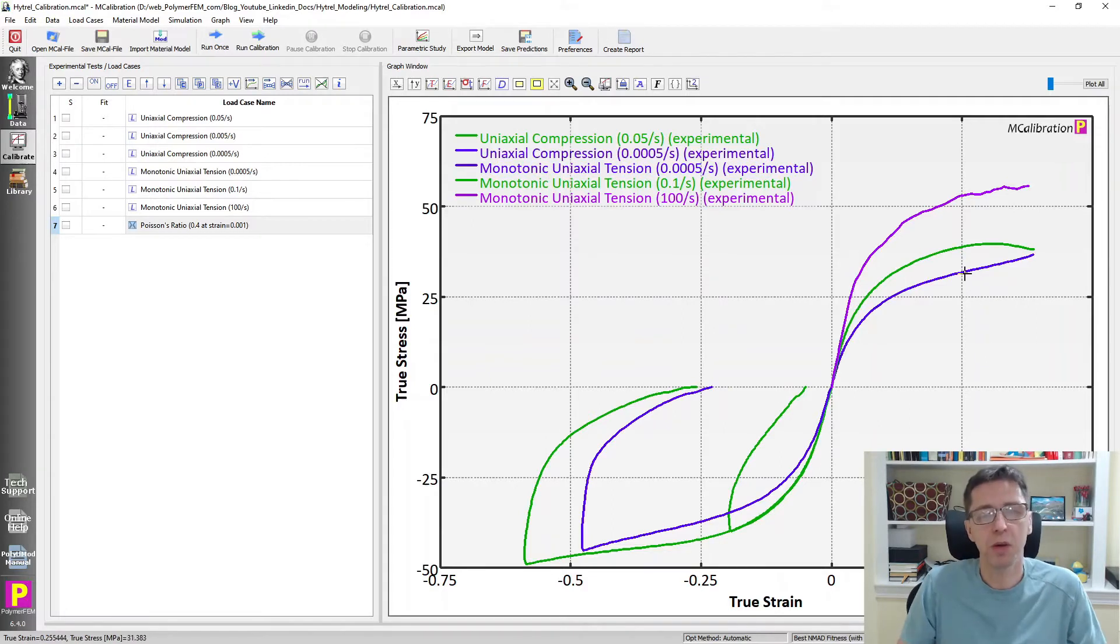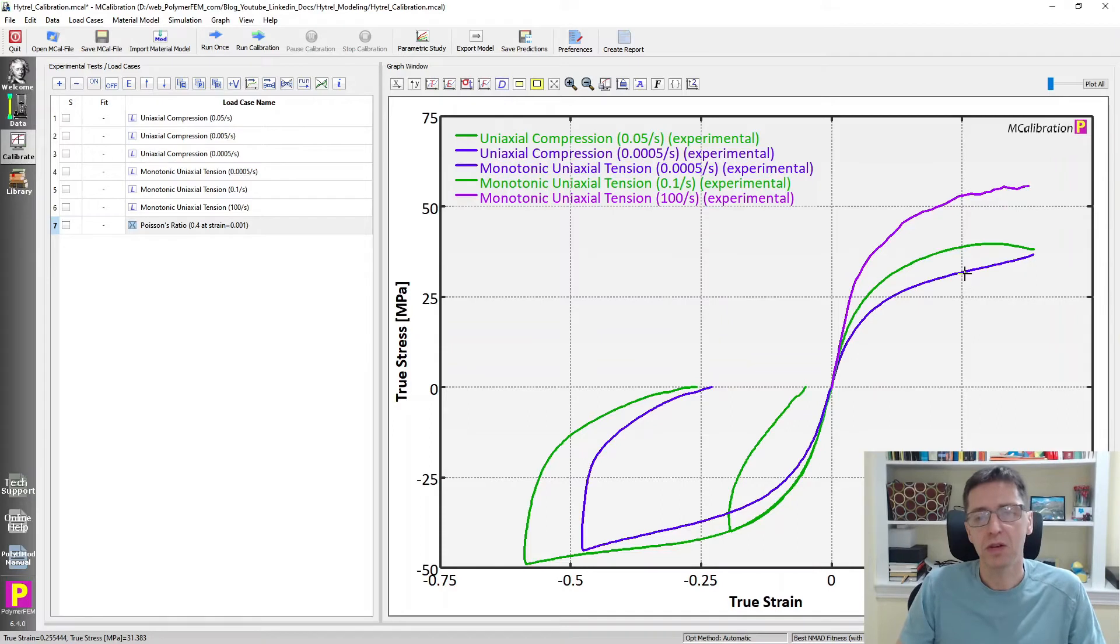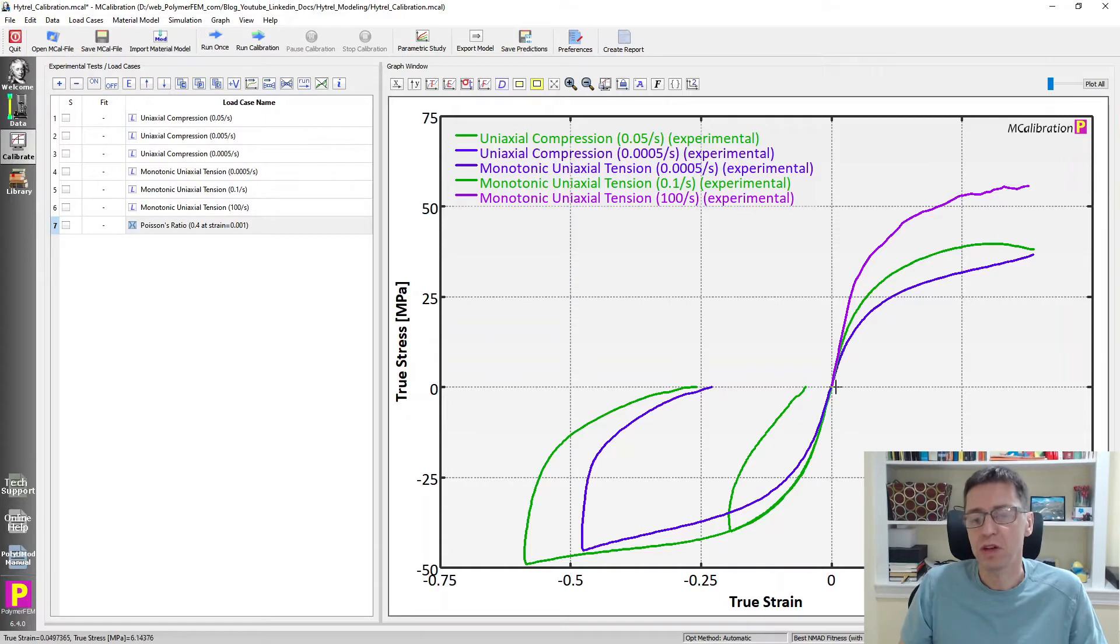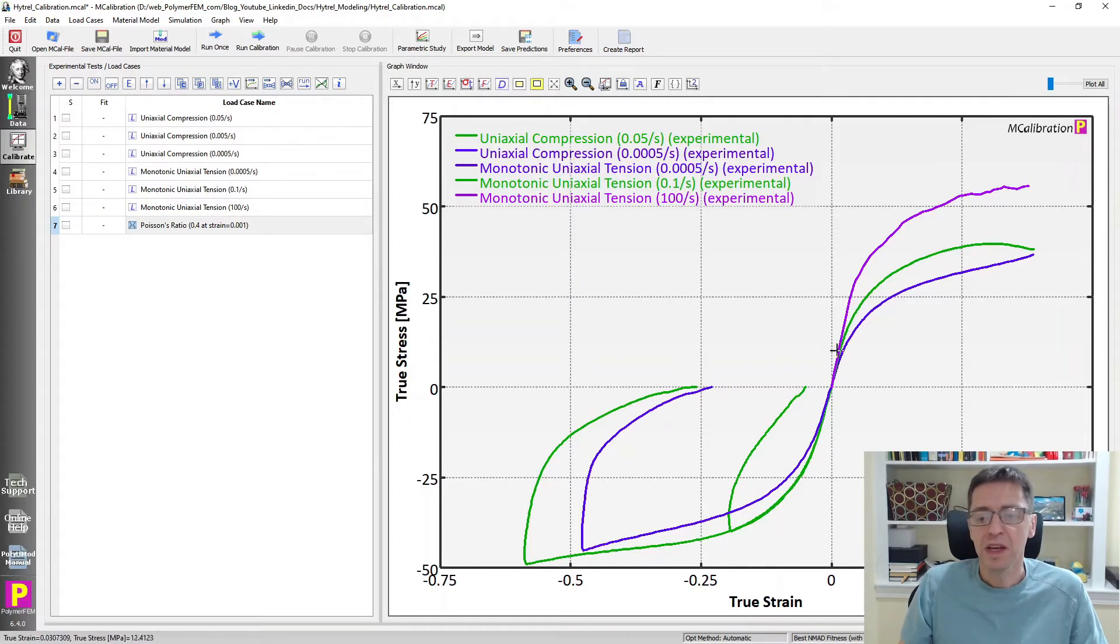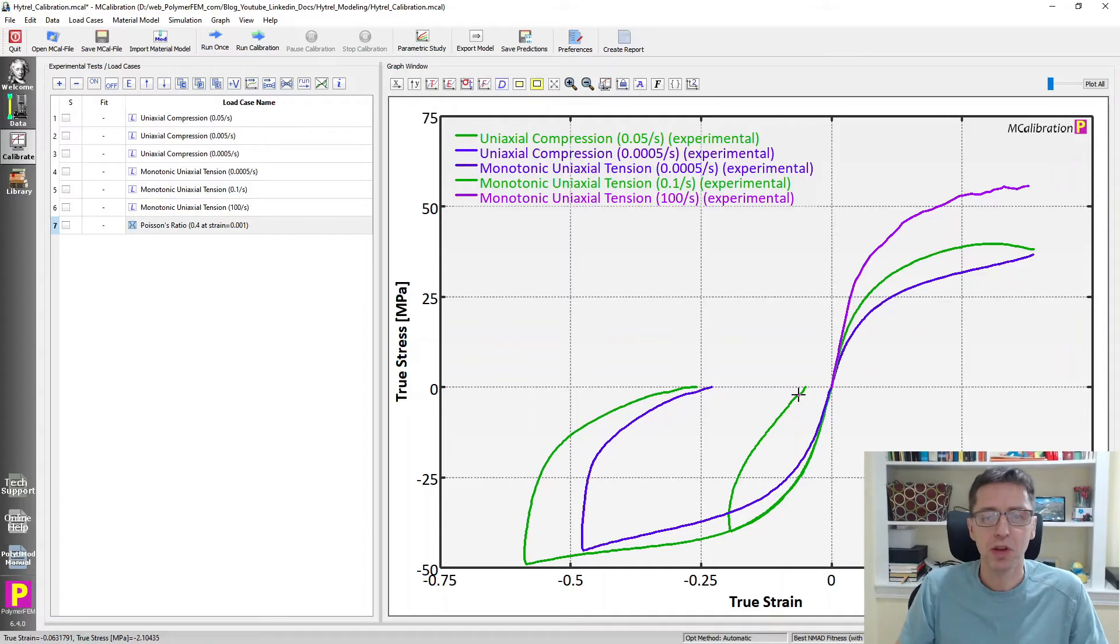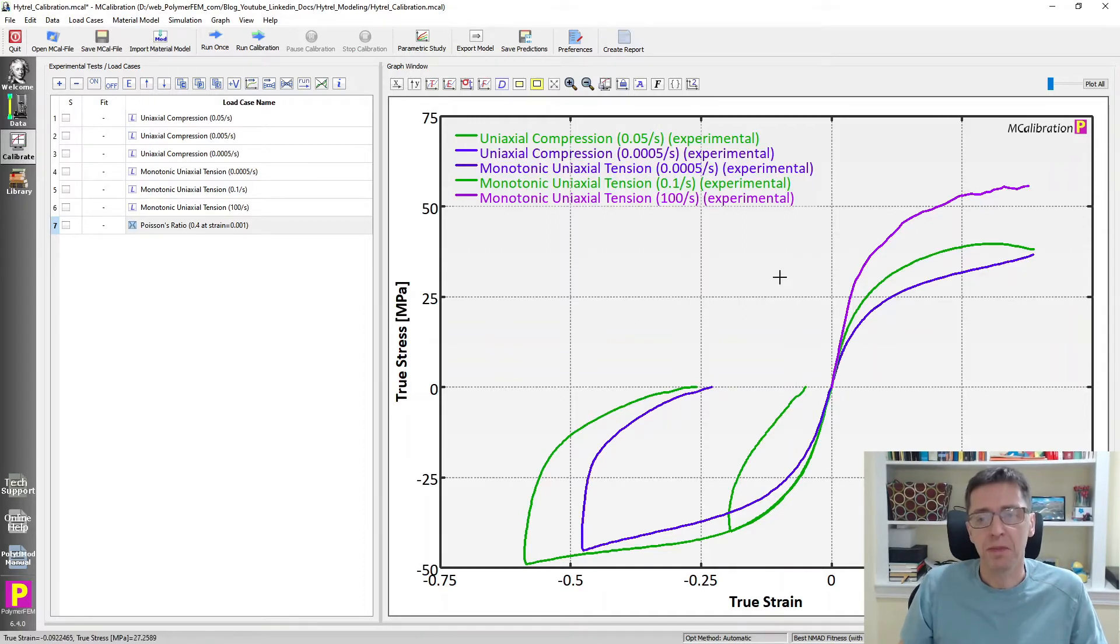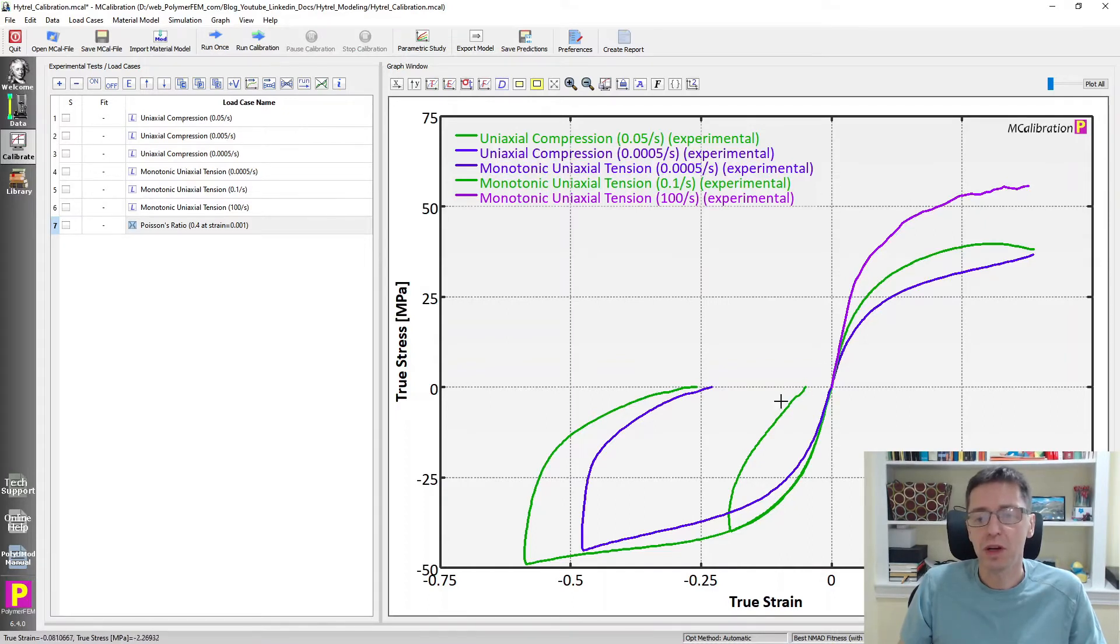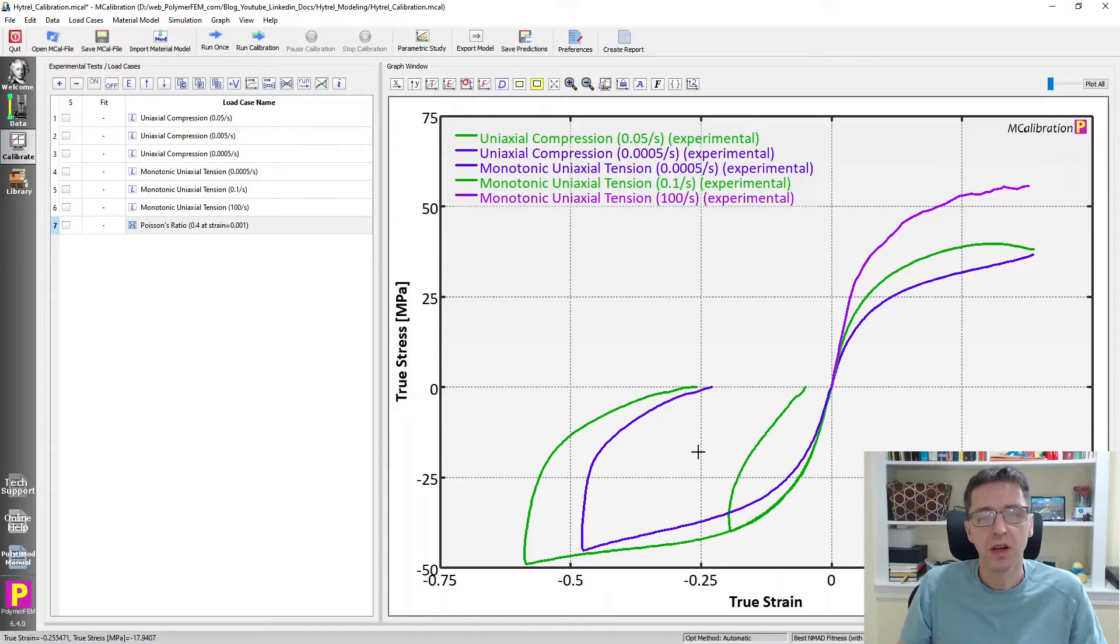So this is relatively common for thermoplastic-like materials, or even these type materials that we're talking about here, they're a little softer, but they still have this asymmetry. So that's why I often recommend doing both tension and compression experiments. So what do I have? We have different tension and compression at different strain rates. I have one really fast tension test, but otherwise relatively slow tension and compression tests.